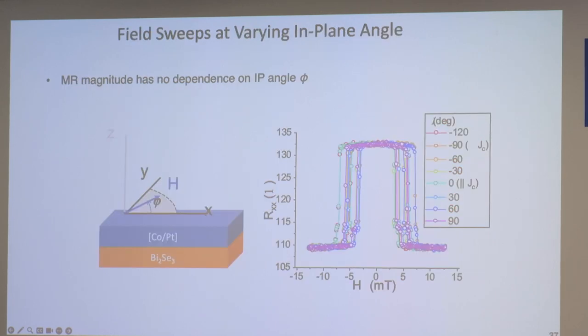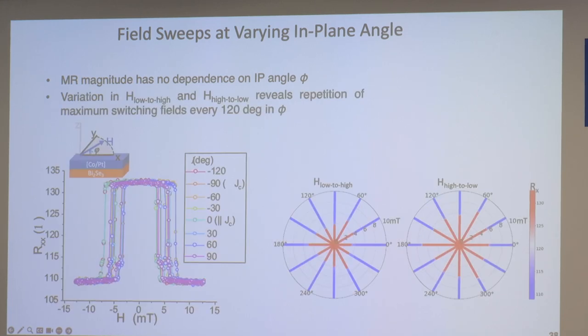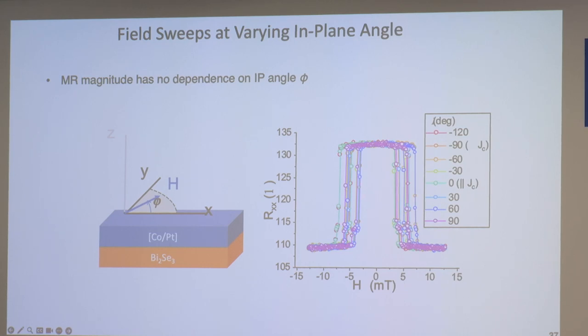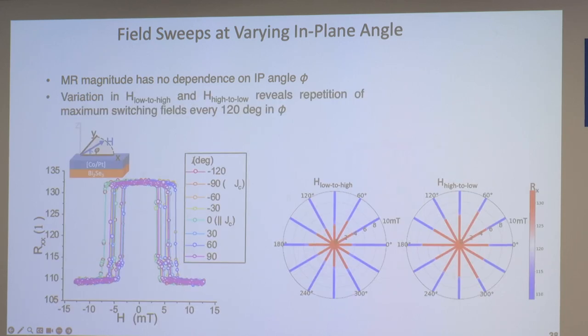Another thing that we noticed that was sort of interesting is that if you look at the magnitude as a function of in-plane angle, the magnitude stays exactly the same. But you see that, if you go to the next slide, I'll go back here actually, you can see that when it switches, it groups into three different switching values, right? So by switching, we're just going up in field, down in field, up in field, down in field, as a function of the angle of the in-plane field. And as a function of angle of in-plane field, we just have three places where it predominantly switches. And we believe that this sort of threefold symmetry in the switching is related to the threefold structure of bismuth selenide. So again, for whatever reason, the magnetic switching mimics the threefold structure of bismuth selenide itself.